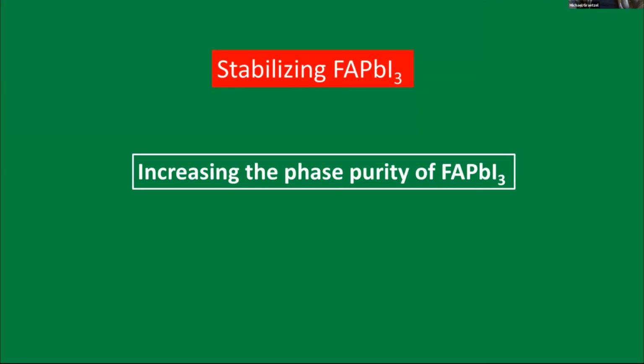And at the very end, I want to mention some ongoing research on the formamidinium. This has been a continuous goal of researchers in the field that don't use the tandem system. The tandem system needs a 1.7 eV band gap. Well, the pure formamidinium doesn't give that band gap. It's much lower, at approximately 1.5. But if you use a single cell device, then you would go for formamidinium, and it's also more stable. And so the question is, can we stabilize the formamidinium without adding too many components that would deprive this material of its favorable properties?